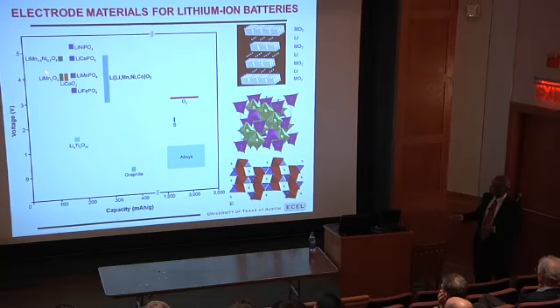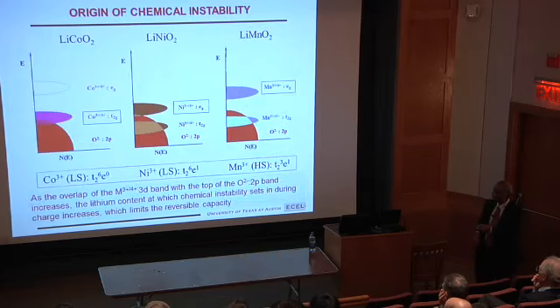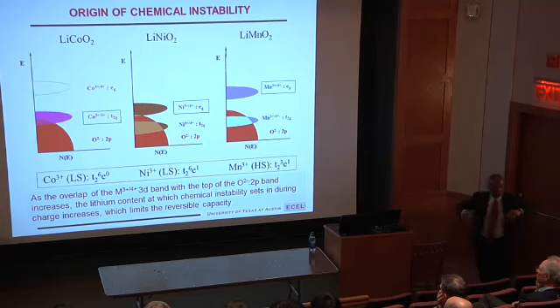These two operate on 3+, 4+ coupled. So the charge transfer gap between the top of oxygen 2p, I think I have a slide here, and the metal here, actually it is overlapping. That has consequences. It's a very small gap, so a highly covalent system. So that has good electron transfer.